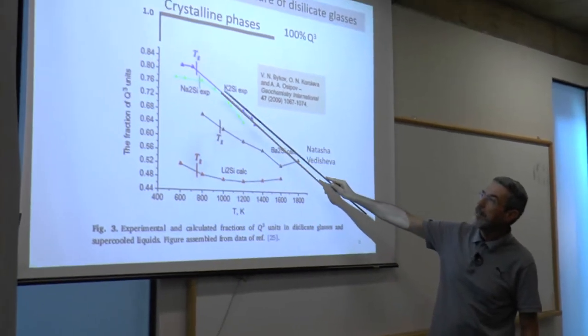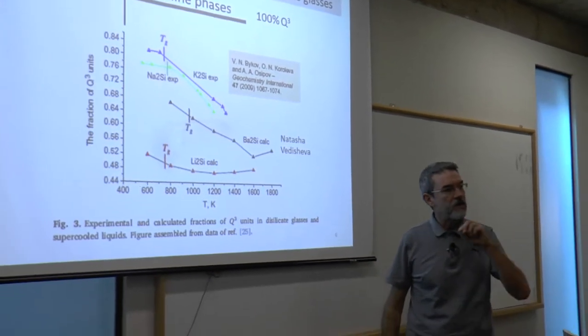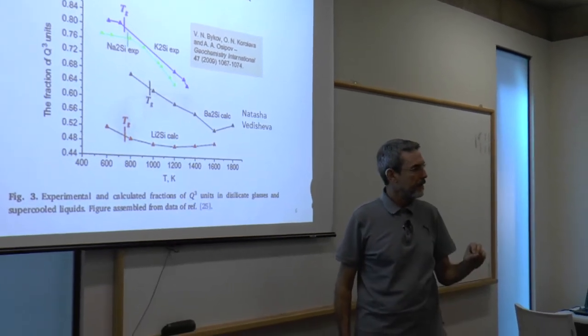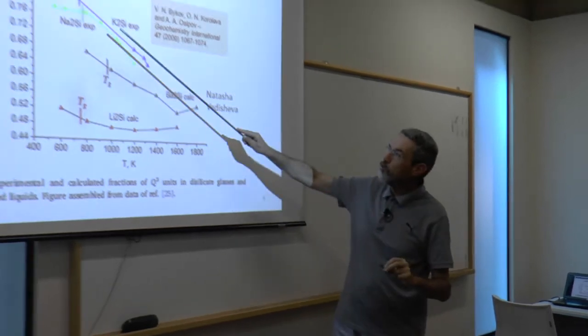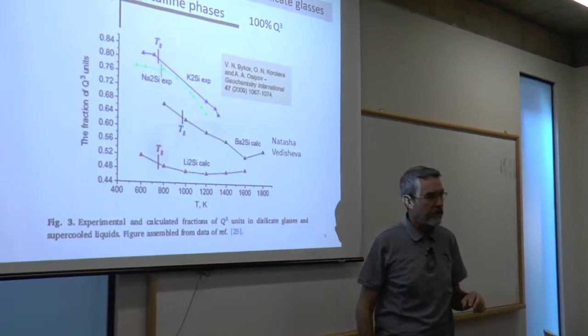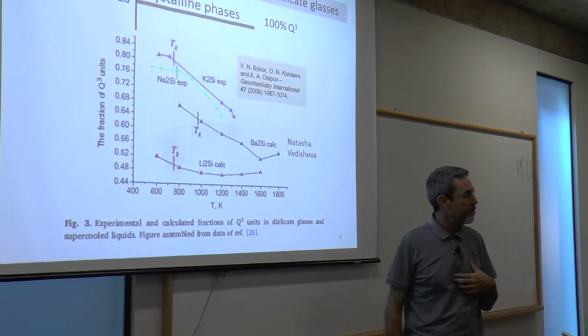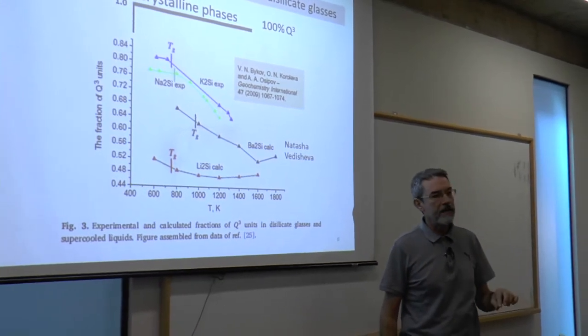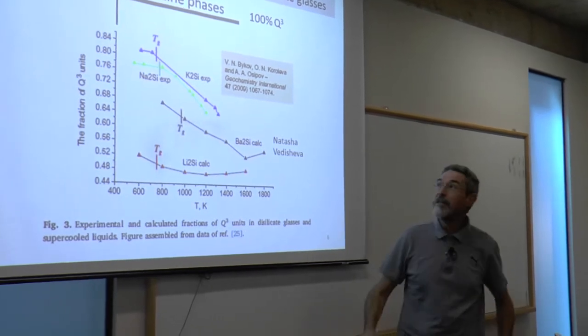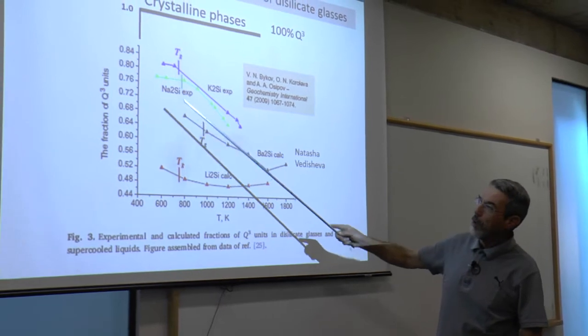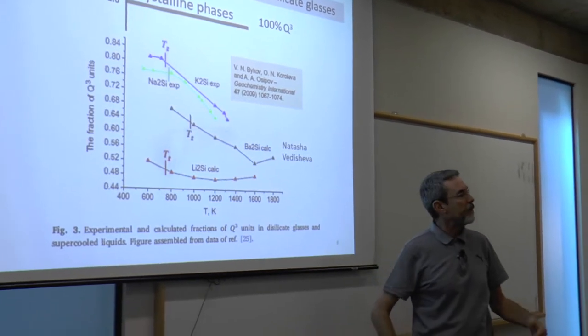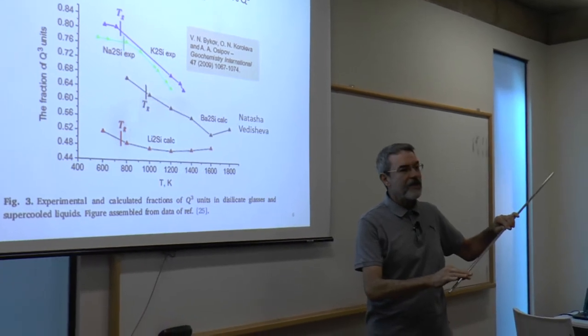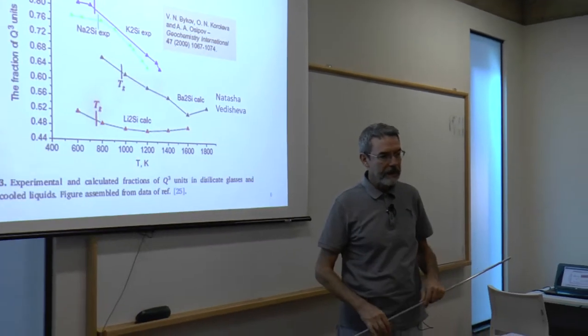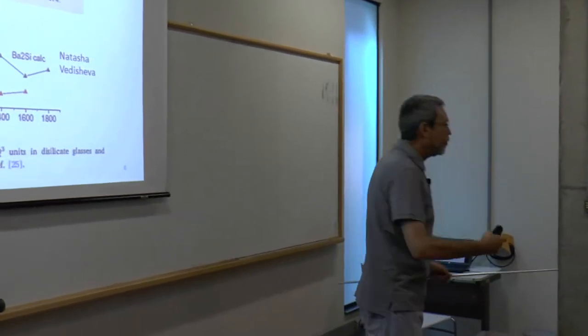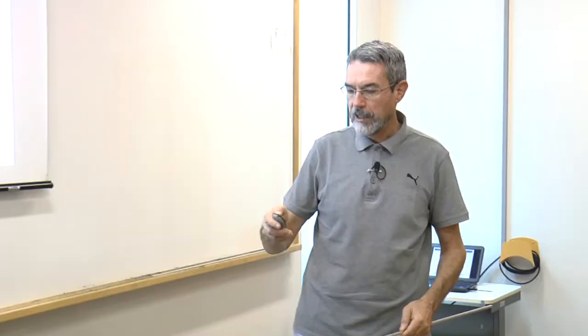And that's why, we have seen that the viscosity curves are not Arrhenian. They are not Arrhenian because the structure changes with temperature of these fragile glasses. So it's not Arrhenian. For a Q4 glass, such as silica glass, the silica glass will be all Q4 and will not change with temperature. So the viscosity curve is Arrhenian, right? So we're starting to correlate structure with properties.